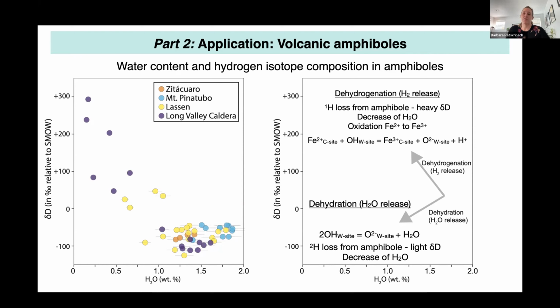It's also associated with a decrease of the water content in amphibole, but it creates a trend towards lighter or lower delta D hydrogen isotope compositions. So we can now plot our data in the water delta D space, which is on the left. And you can see right away that the majority of amphibole compositions basically plot in a relatively narrow field, around 1.58% water and negative 80 per mil. Exceptions to these are some amphiboles from Lassen and the Long Valley caldera, which show this trend towards lower water contents and heavier hydrogen isotope compositions.